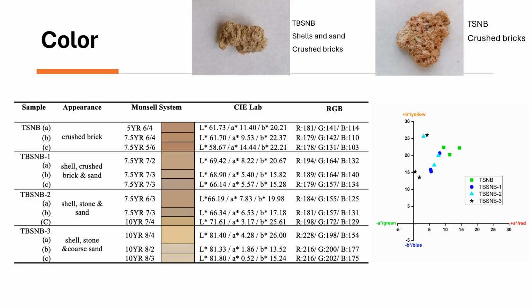In this slide, the table presents the results of the in situ characterization of the walls. It is observed that the appearance in the center of the wall in TSNB is 7.5 YR 6 over 4. TBSNB-1 is 7.5 YR 7 over 3. TBSNB-2 is 7.5 YR 7 over 3, and TBSNB-3 is 10 YR 8 over 2.